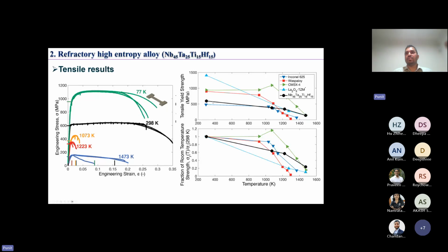If you look at this, this is niobium, tantalum, titanium, hafnium. You can see the starting strength at room temperature is quite low, but the material retains its strength very well up to 1200 degrees C. And now you can see it's almost comparable to single crystal nickel based superalloy at 1200 degrees C. And if you normalize these strength values and compare the strength retention, you can see that NTTH actually shows better strength retention compared to the existing materials that we use at high temperature. So this was really interesting.